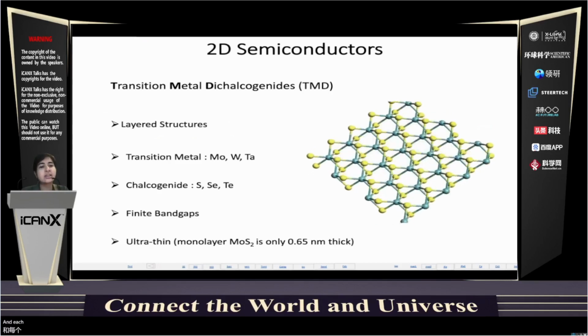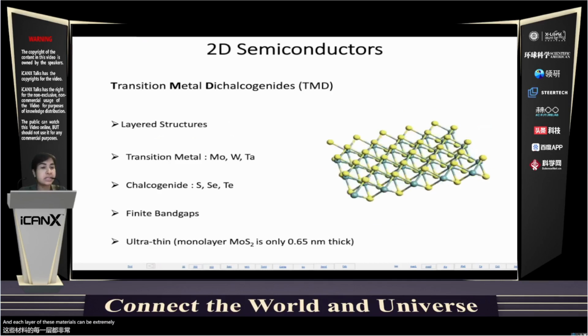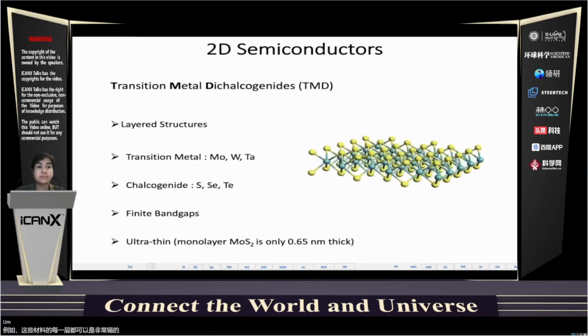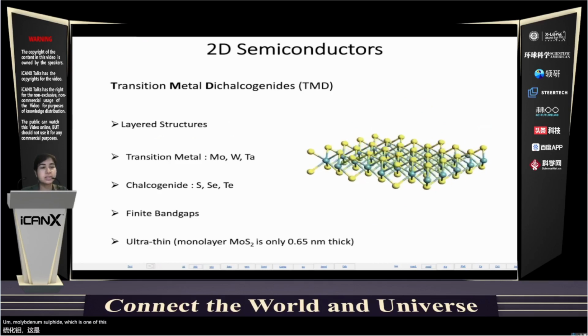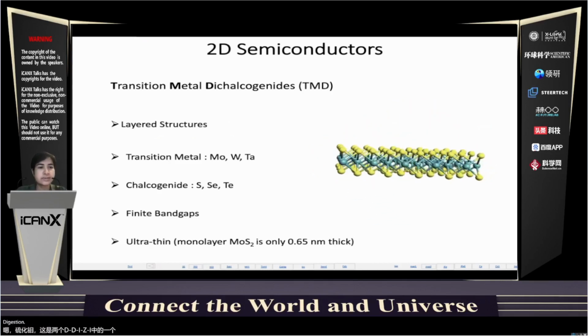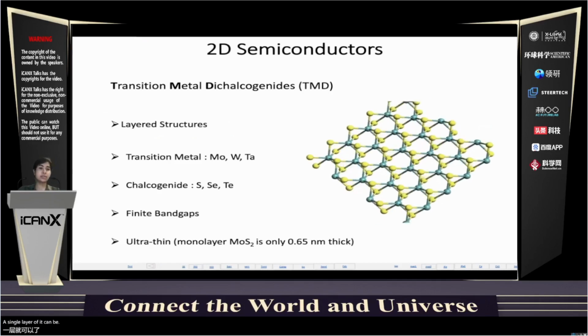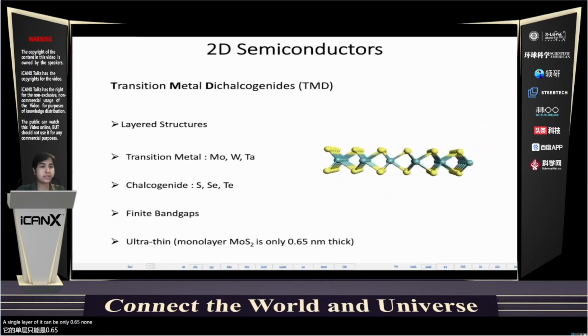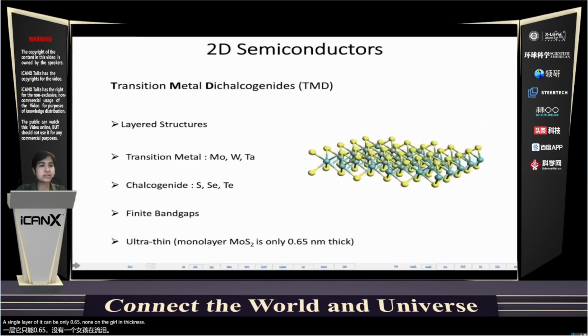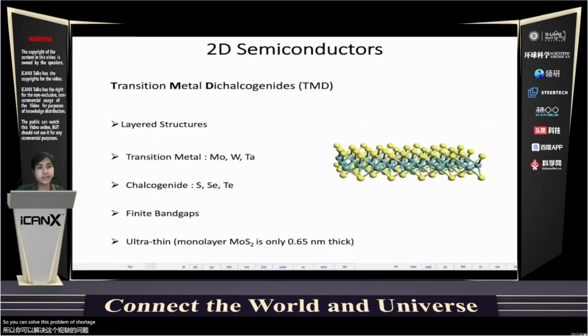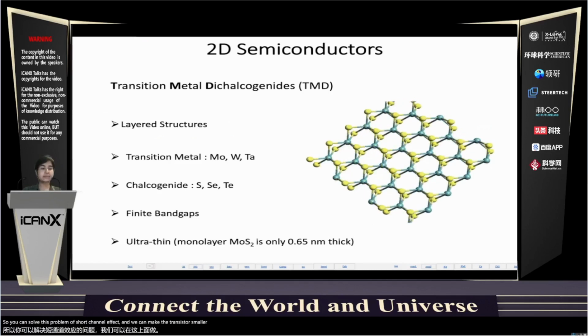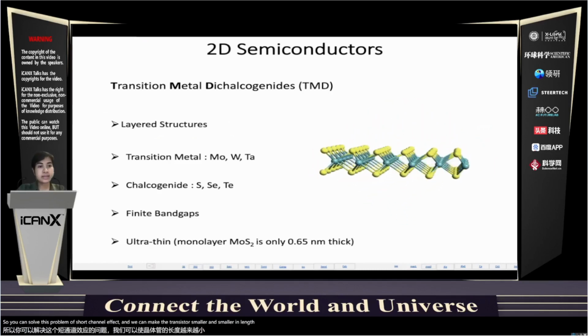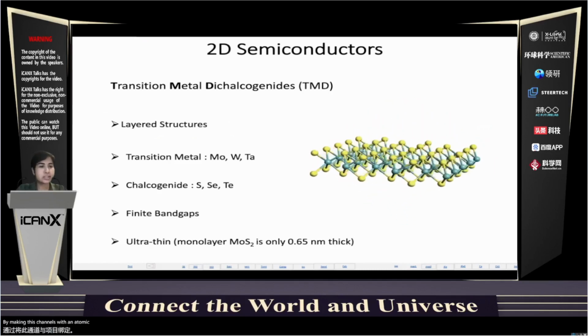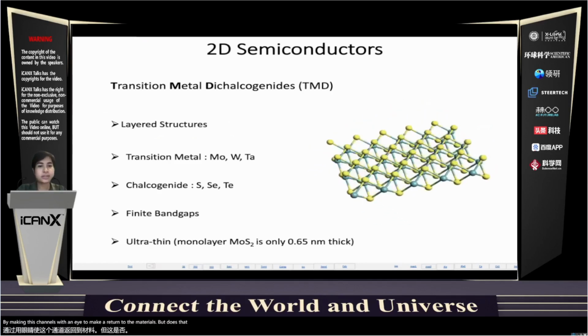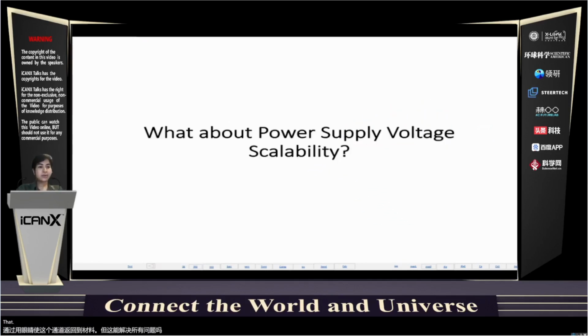And each layer of this material can be extremely thin. For example, molybdenum disulfide, which is one of these 2D transition metal dichalcogenides, a single layer of it can be only 0.65 nanometer in thickness. So you can solve this problem of short channel effect, and you can make the transistor smaller and smaller in length by making these channels with atomically thin 2D materials. But does that solve all the problems? That solves the problem to some extent, but not all.